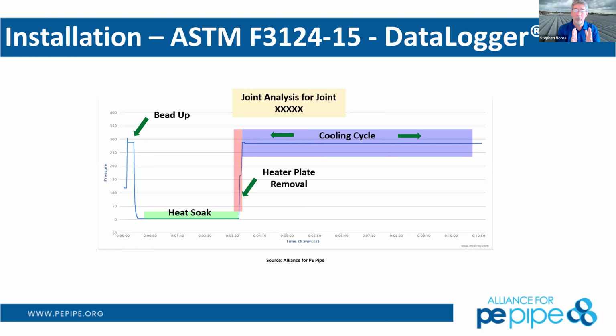Now what you have to do, though, is hold that interfacial pressure during the cooling cycle to make sure that it doesn't move or get pulled apart while it's going from that molten phase to the solid phase and then cooling back down to a temperature that you can then take it out of the fusion machine and start moving it around.